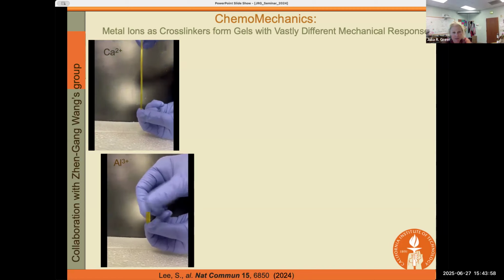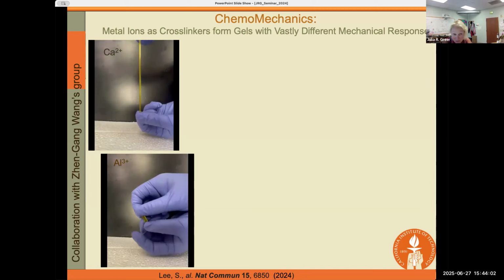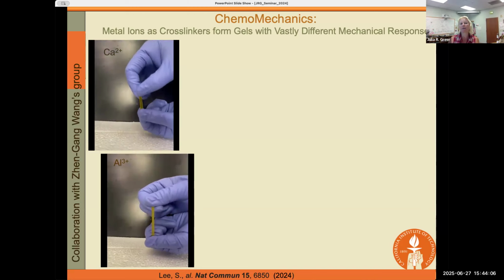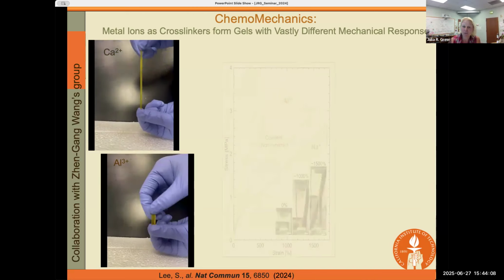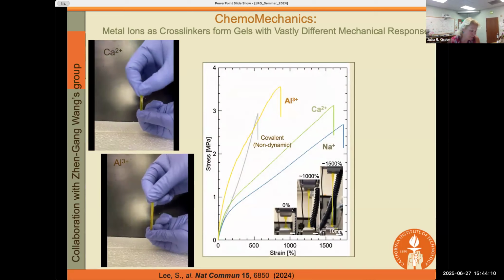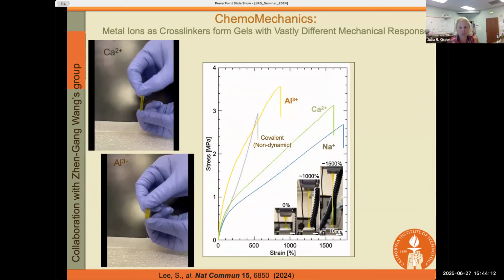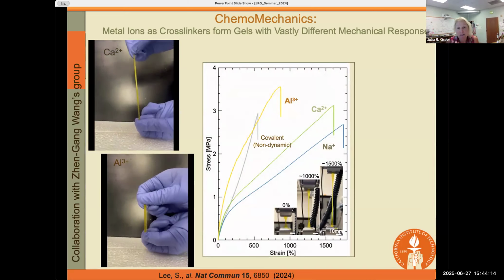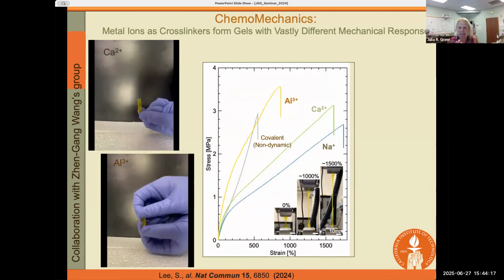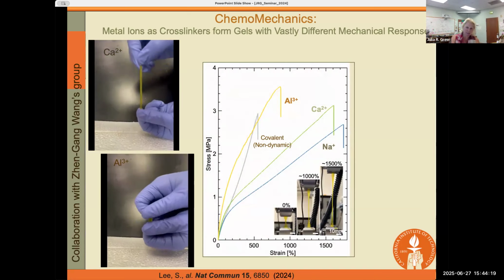And you can see from this highly technical experiment that the aluminum one is very stiff and not very stretchy. And the calcium one, again, it's the same resin, the same polymer resin, but infused with a different metal ion, is very stretchy. Now, in more technical terms, we now compared the divalent to the trivalent to the monovalent response. And you can very clearly see that that's a key parameter that makes a huge difference in the mechanical response.